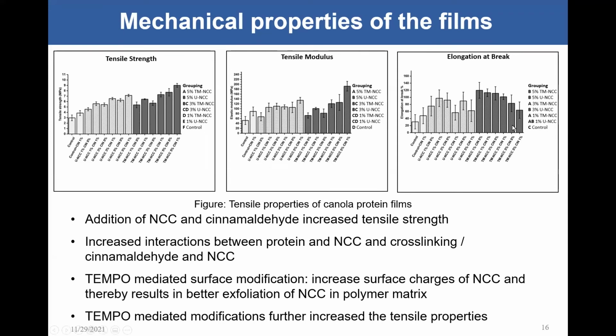The other important thing is about the elongation at break. This is something that we normally observe with all the canola protein-based films. When we increase the amount of nanomaterials, they normally tend to reduce the elongation at break, but still, compared to the control, it's better at 5%. But if you work with, let's say, 3% nanocellulose, there is a significant improvement of the elongation at break as well.